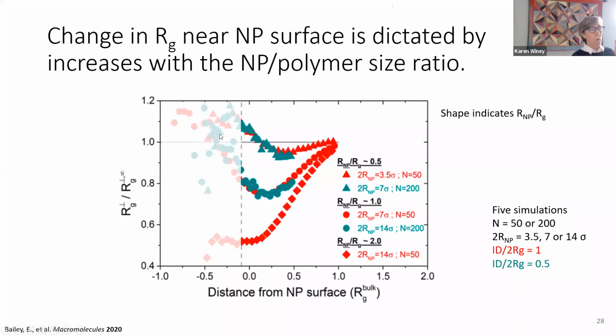Yeah, and then these are the particle, all these. Is the polymer wrapping around, is that why it's getting denser? Because it kind of hugs the nanoparticle? It conforms to the surface? It's not getting denser, just like when the chain conformation was distorted at the wall of the thin film, it's not getting denser. The bead density is the same in the simulations. It's just that it's taking a different random walk. It's taking a flatter random walk. And then, Seth, the shadowy particle points correspond to the chains that are wrapping around a particle, because then their center of mass is interior. Yeah.